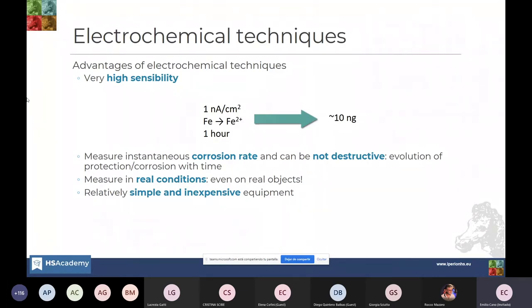This, that electrochemically can be measured quite easily, produces a change of mass of only 10 nanograms, which is extremely difficult to measure. So this is one of the advantages, the high sensitivity. Another very important advantage is that we can measure the instantaneous corrosion rate. We do not measure the accumulated corrosion over a long time, but we can measure it instantaneously at different times during the corrosion process.